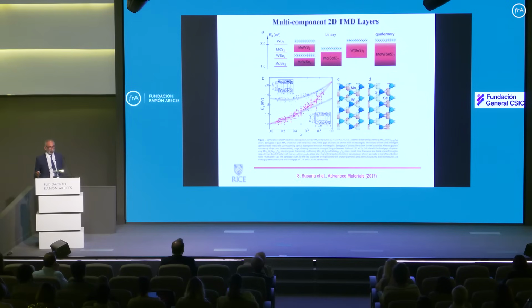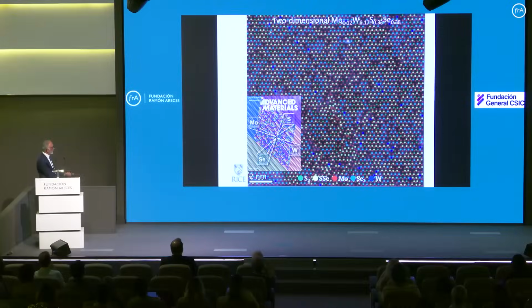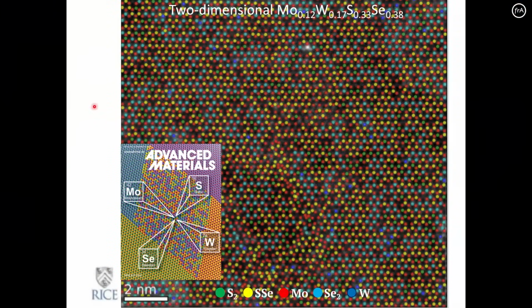And not only that, you can also make multi-component two-dimensional materials. We mostly started talking about graphene, then we talked about two components, boron and nitrogen, or things like molybdenum and sulfur. But you can have multiple elements in a 2D material. I'll show you just one image that shows a material. This is an atomically thin, single unit thick material that has molybdenum, tungsten, sulfur, selenium, really uniformly distributed throughout the structure.